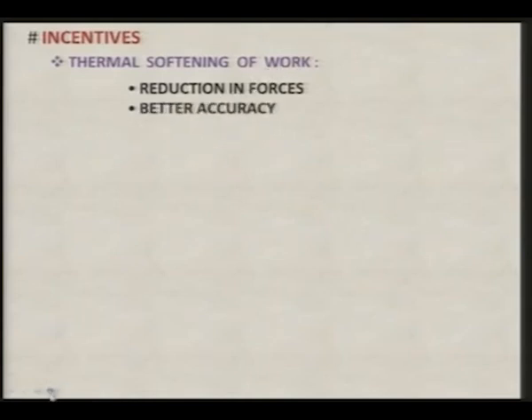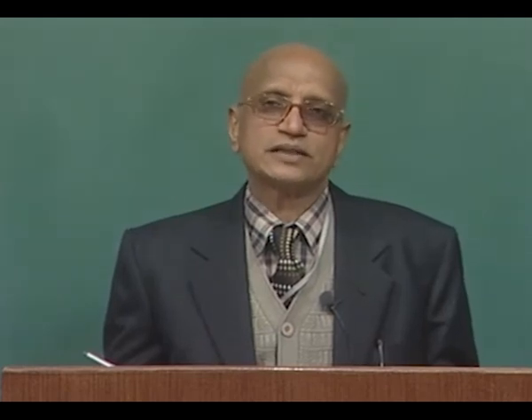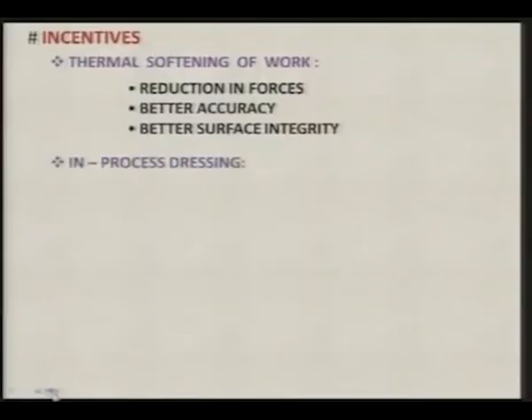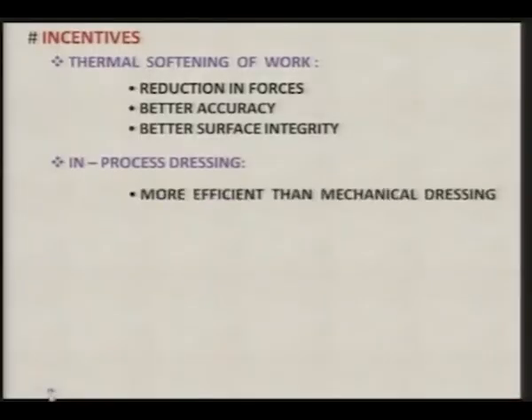You can achieve better accuracy on the finished component and better surface integrity, because once the material is soft and you are removing the material, the probability of micro cracks and thermal residual stresses goes down. Now, in case of electric discharge abrasive grinding as well as electric discharge diamond grinding, I will show you in the following slides that in-process dressing takes place without performing any additional dressing operation manually. This in-process dressing is more efficient than the mechanical dressing which I explained.